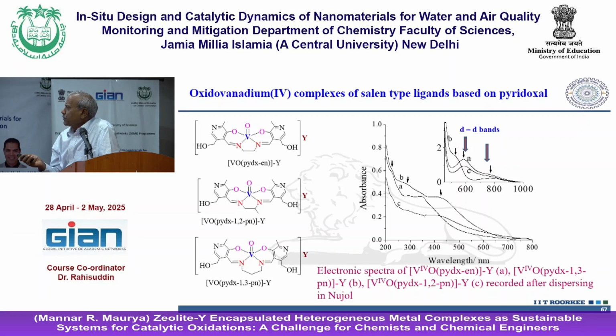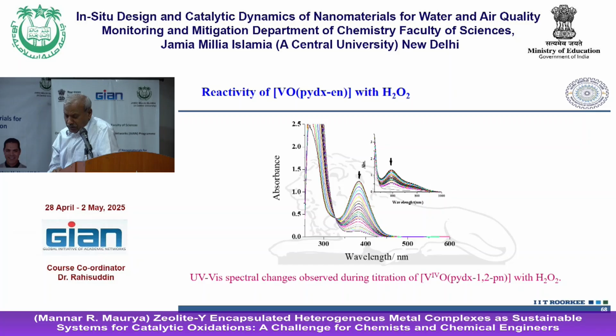Now, as I mentioned, the H2O2 titration: you will see very clearly one isosbestic point, and that isosbestic point is a clear indication that even this VO compound, even with this Schiff base type ligand using pyridoxal as a side arm, is giving almost similar results and converting.